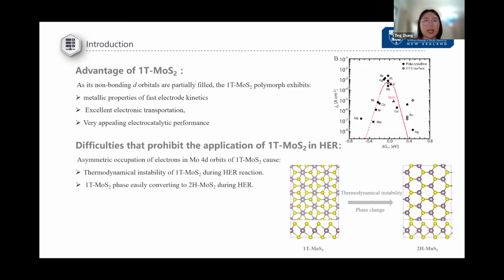One is called 1T-MoS2, and the other is called 2H. For 1T-MoS2, the non-bonding d orbitals are partially filled, and there are only 2 electrons distributed in the Mo 4d orbital. So it exhibits specific properties: it shows metallic properties, and it allows electrons to transfer really fast in the catalyst. It also has really high HER activity. But 2H MoS2 is a traditional semiconductor. It doesn't have any HER activity, and the conductivity of 2H MoS2 is quite low.